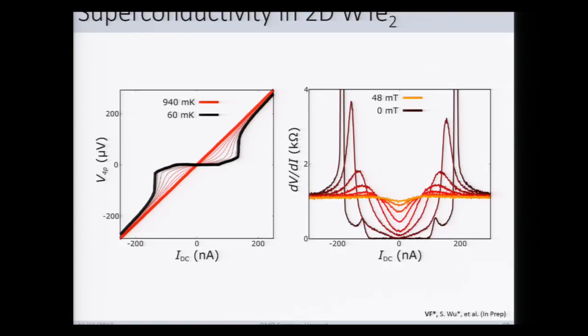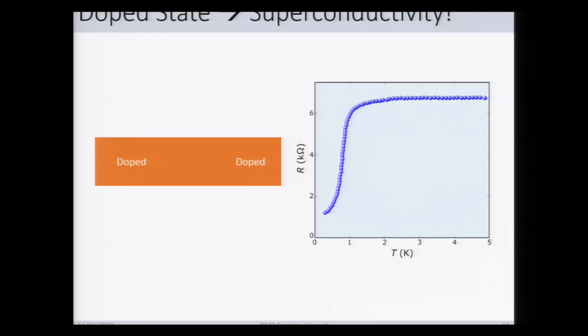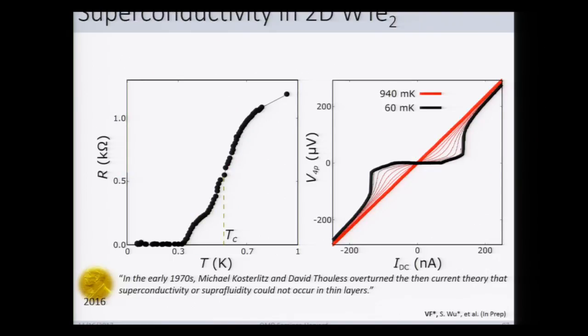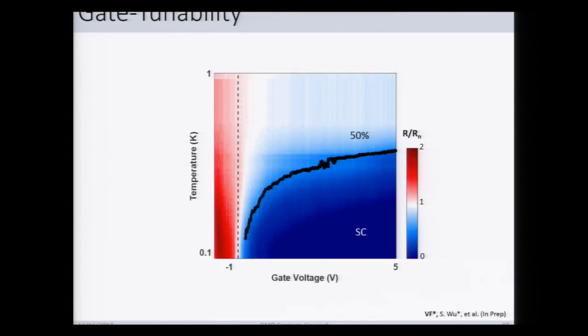Now, what I described a minute ago was that we just have to dope the system to reach here. And I've already shown you that we can also dope into the insulating, the topological insulator phase. So I can show you, for example, the temperature versus gate voltage diagram of the relative change of resistance compared to high temperature. And we see that, at high doping, we undergo the same superconducting transition where we reach zero resistance, again, at around 300 millikelvin at high density.